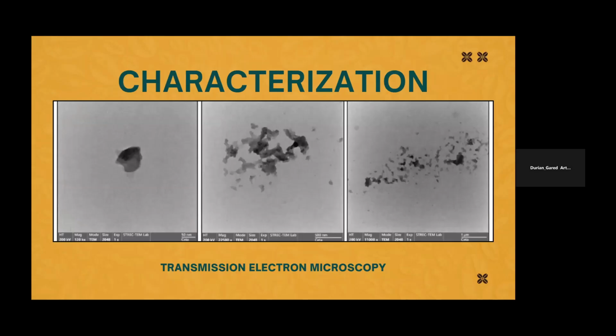Then here we have the morphological features of the GOQDs that were validated through transmission electron microscopy. So TEM observations at 1 micrometer, 500 nanometer, and 50 nanometer field of view allowed for an accurate assessment of their structure and dimensions. The measured size of the GOQDs was determined to be approximately 20 nanometers, aligning with the typical size range of GOQDs, which are generally characterized by dimensions below 30 nanometers.